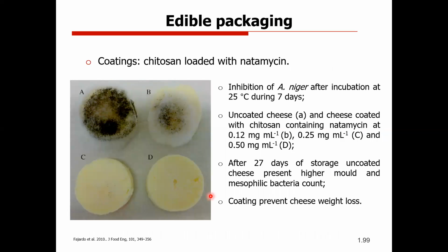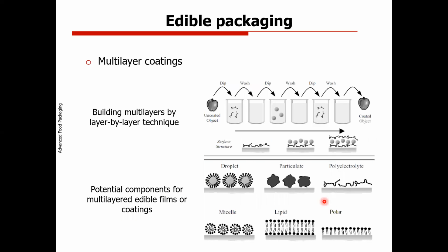We are also able to add some compounds, in this case, a chitosan coating loaded with natamycin at different concentrations. You can see A, B, C, and D with increasing concentrations. And we were able to decrease the microbial growth and inhibit this fungus during 7 days. It was also able to decrease the cheese weight loss, which in cheese is one of the problems. So this coating also acts as a barrier to water vapor and to the weight loss of the product.